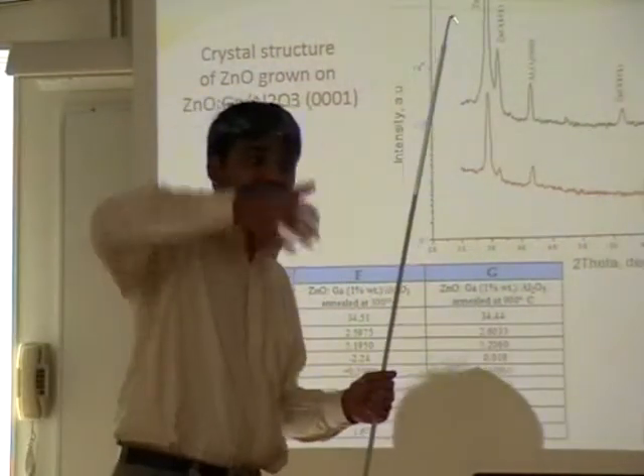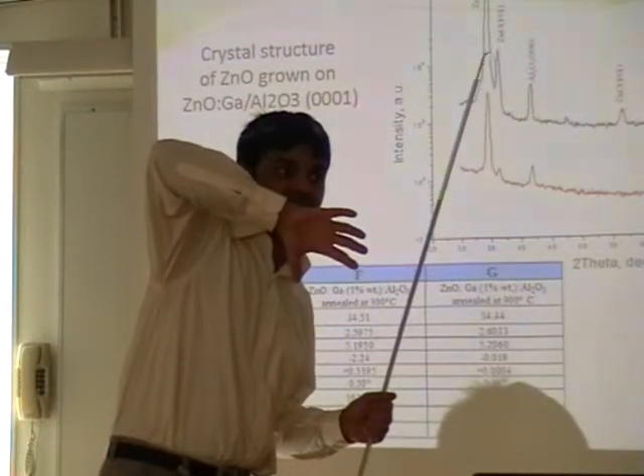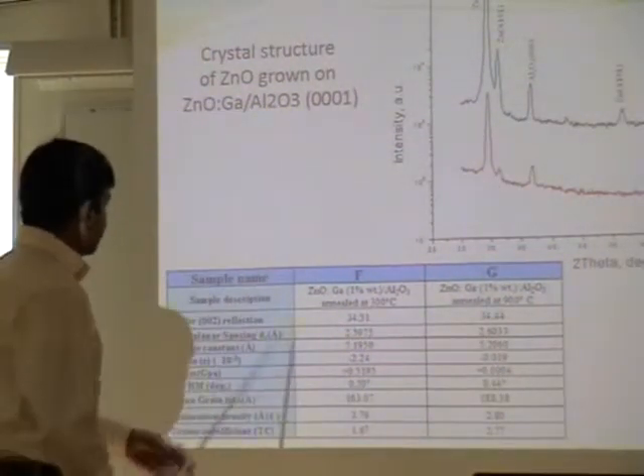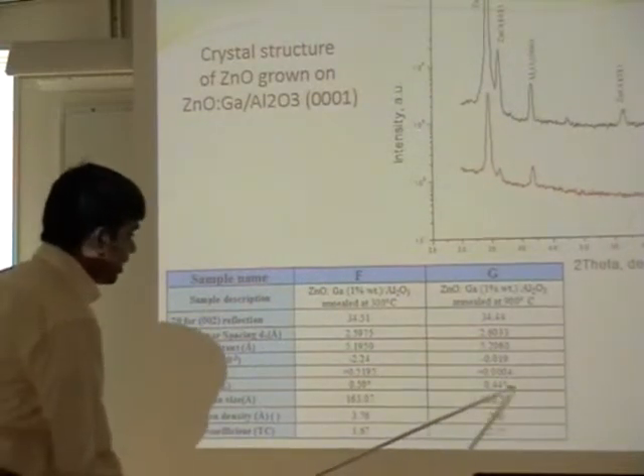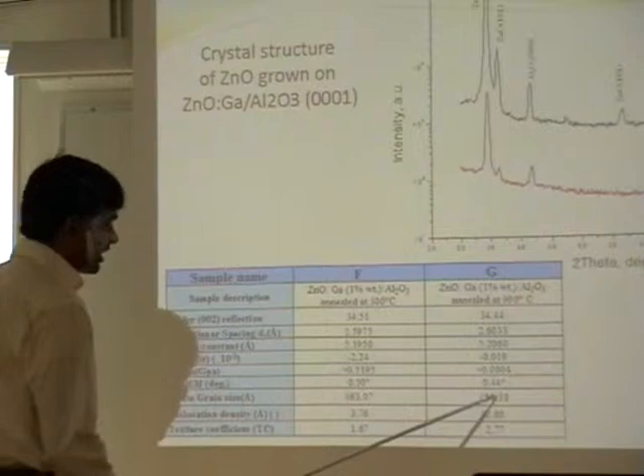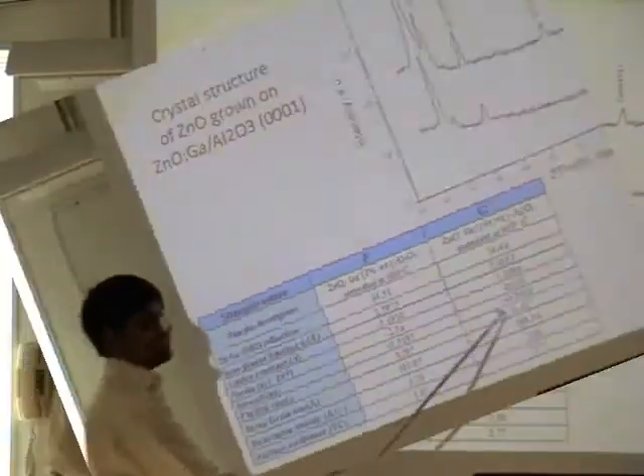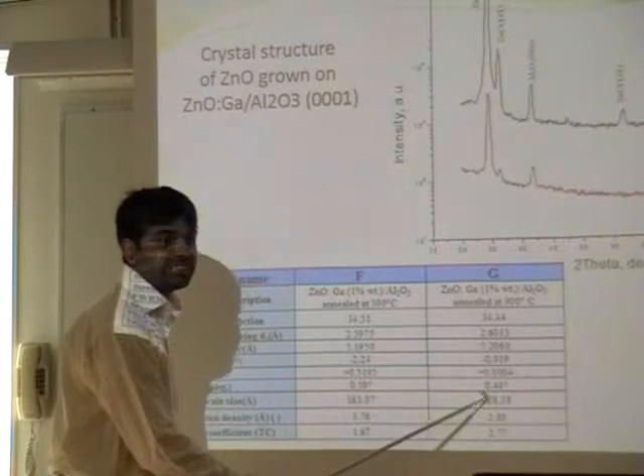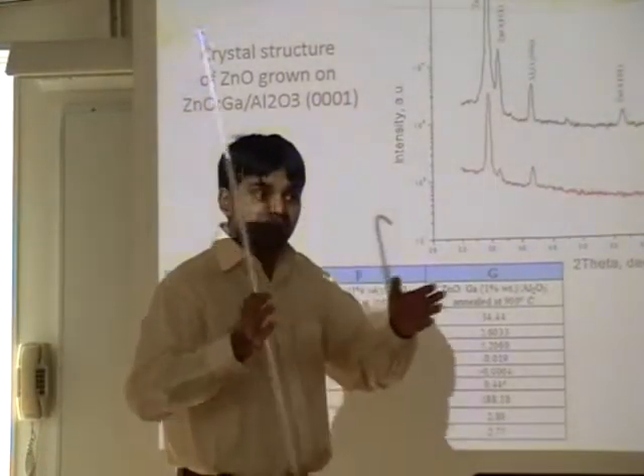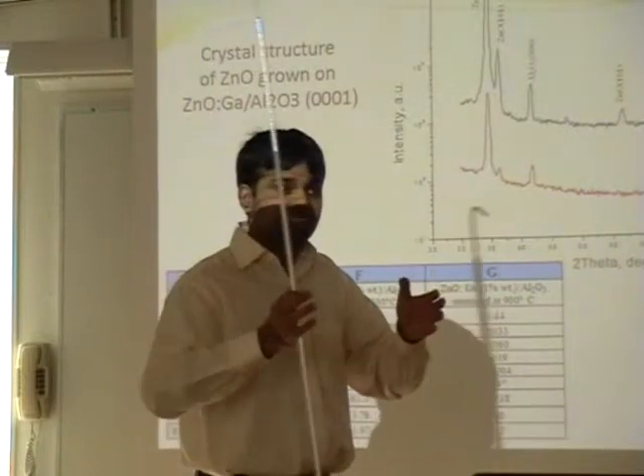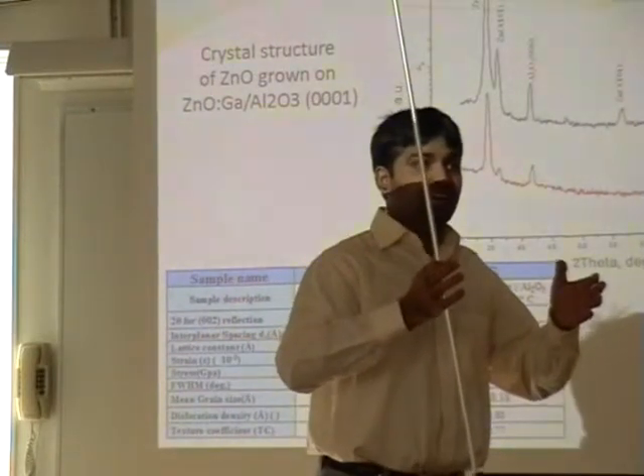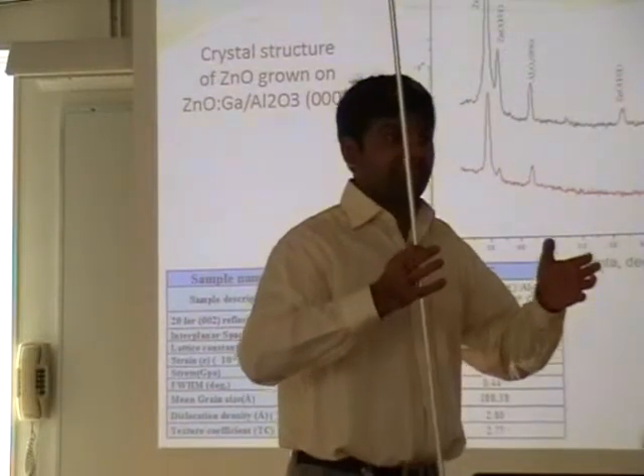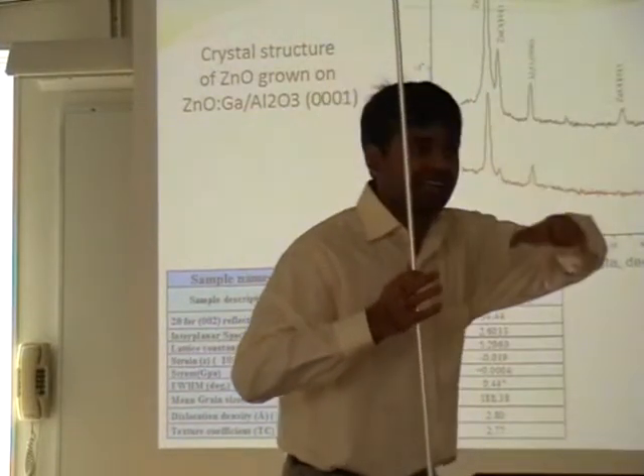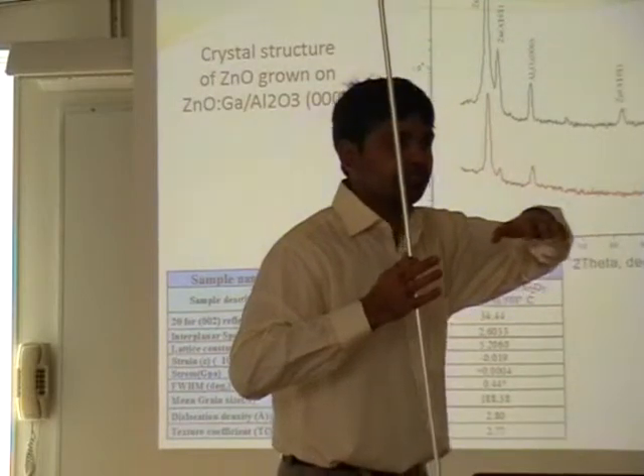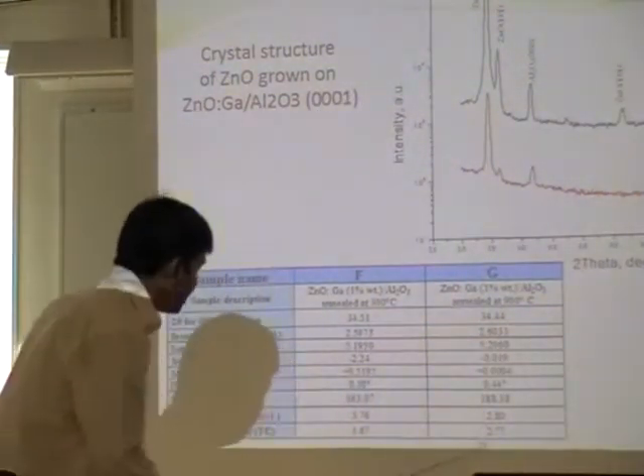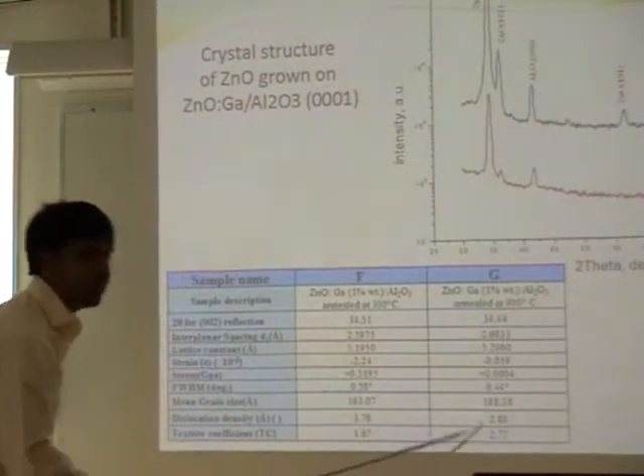After annealing, then again grow the zinc oxide. Here you can see, grain size increased at annealing 900°C. The reason, the crystal dimension becomes larger. Concentration of the point defect and impurity can be eliminated at higher annealing temperature. And for the film, here you can also see the texture coefficient also increased.